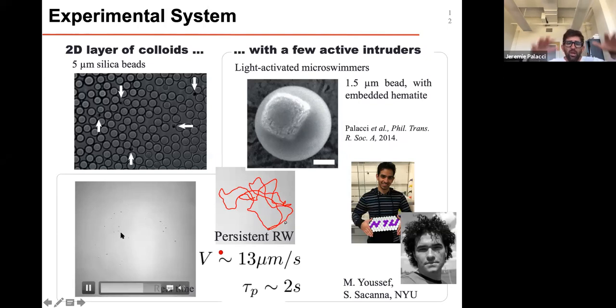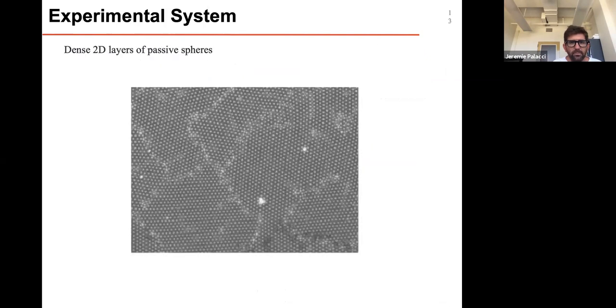If you put those particles in, they're heavy, they sediment near the bottom substrate. And if you shine the light, they do a persistent random walk, which means that they self-propel with a speed of typically 13 microns per second and change direction every 2 seconds, which is set by Stokes-Einstein rotational diffusion. And that's the behavior we can see. So you can see this persistent random walk is very different from thermal Brownian motion, for example.